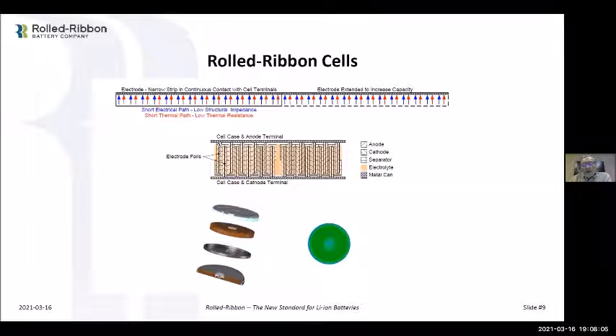So basically you have the edge of the metal here. So it's metal to metal when you do that. And we do it under pressure. And then you have this massive amount of surface. The entire edge of this electrode, this spiral wind that you see here, that entire edge is in contact with one band. And the opposing one has a spiral wind that comes out the other side of the Z-fold, and it's in contact with that. And then we put this under pressure. And so that gives us a very low impedance between there.